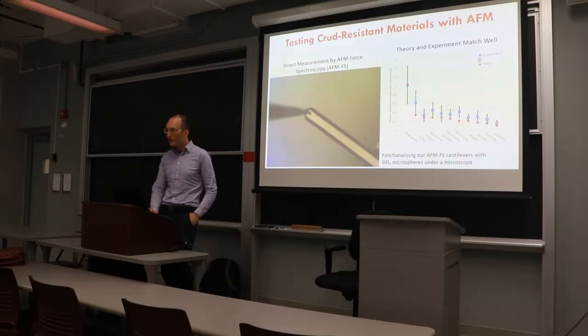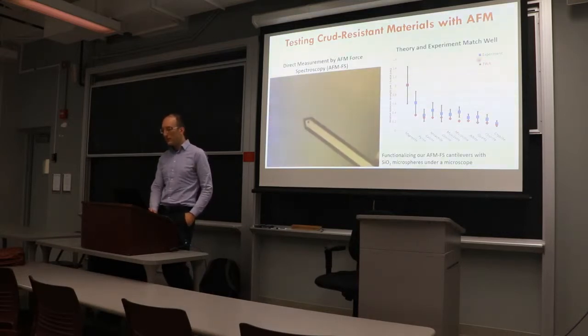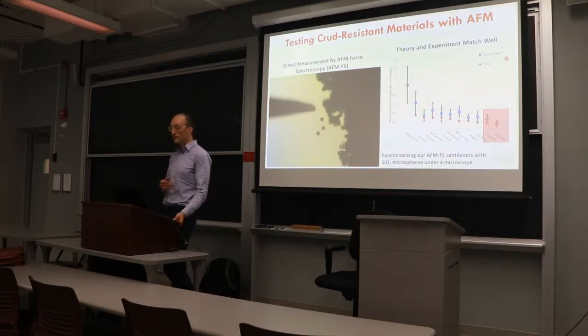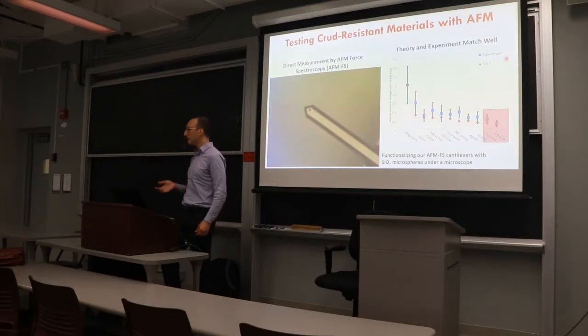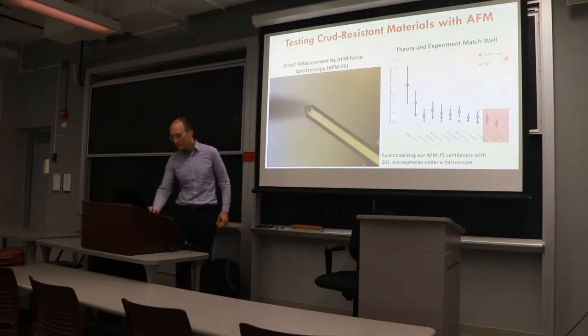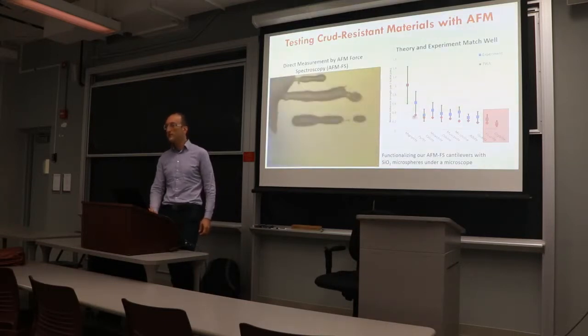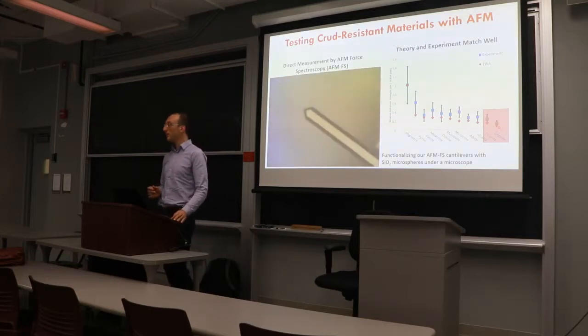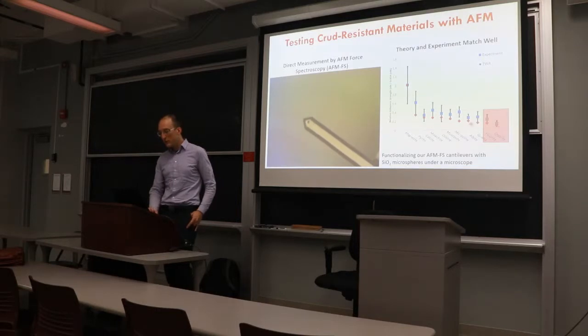And luckily, our theoretical predictions in red and the experimental results in blue match up pretty well, especially for the really slick materials. We're able to make things that are routinely 20 to 50 times less sticky than zircaloy cladding. You'll notice there's always a little bit of a mismatch between the experiments and the simulations. That's because there are other surface forces at play, but van der Waals forces appear to be the dominant one, as is the mostly good agreement between experiment and calculation.